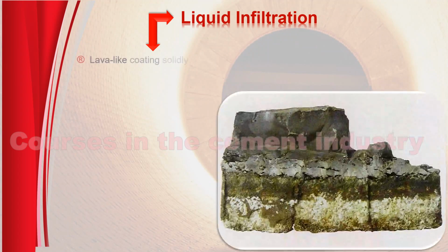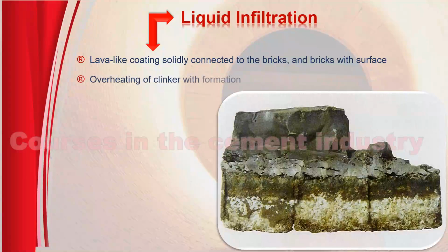Liquid infiltration. The main reasons for this are: 1. Lava-like coating solidly connected to the bricks, and bricks with a glazed surface. 2. Overheating of clinker, with formation of liquid. 3. Increased liquid phase, infiltrating the hot face.